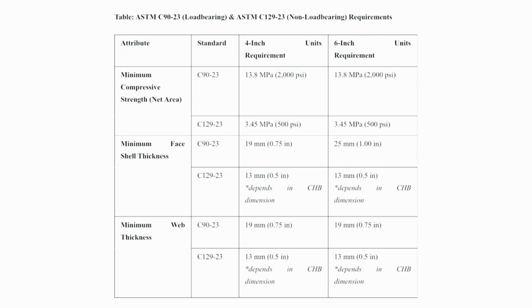Likewise, the 6-inch CHB satisfied the web and shell thickness specifications of ASTM C90-23, and both thicknesses satisfied ASTM C129-23. These findings indicate that the CHBs are dimensionally sufficient under ASTM C129-23, which is for non-load-bearing units, but could be limited in load-bearing use under ASTM C90-23.